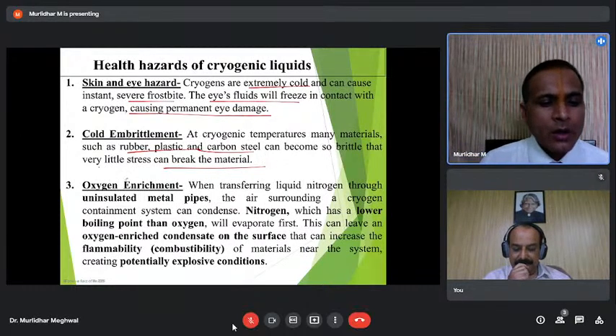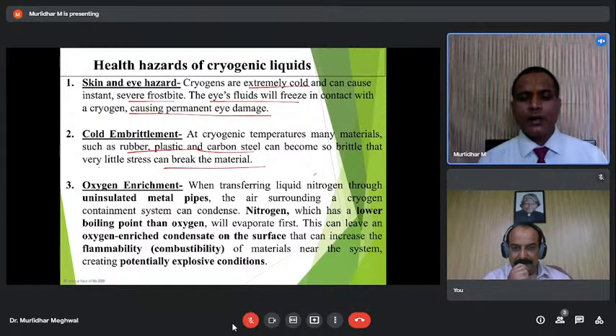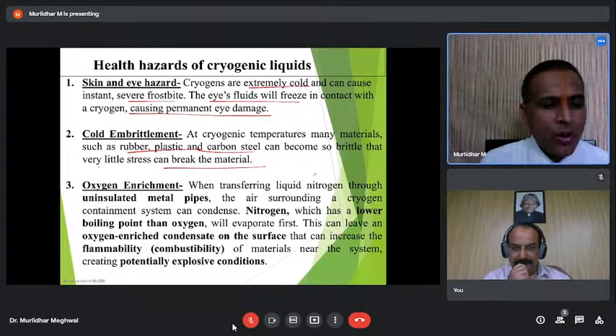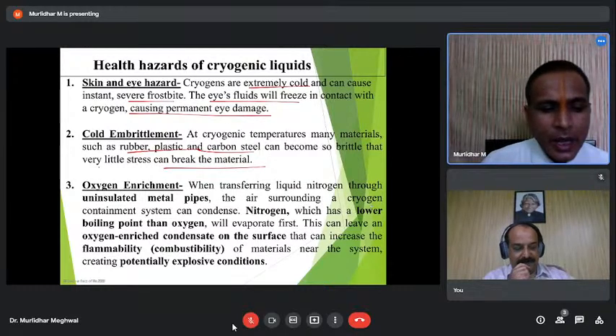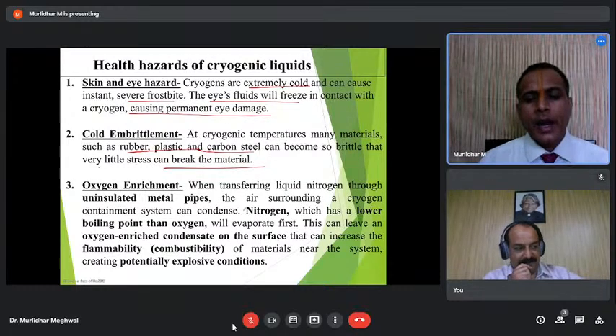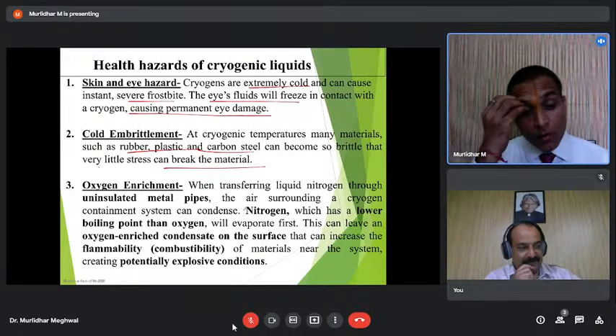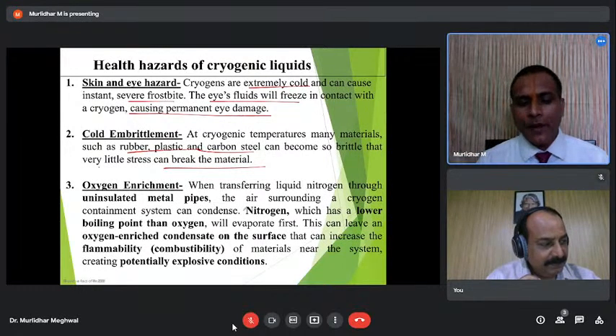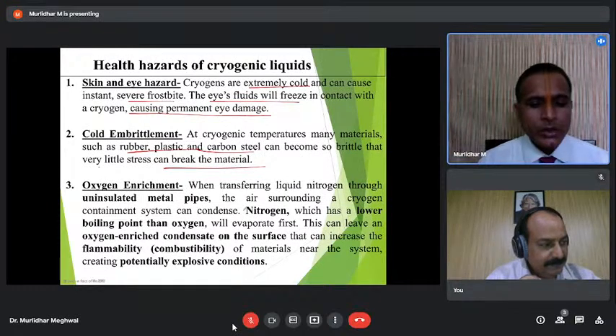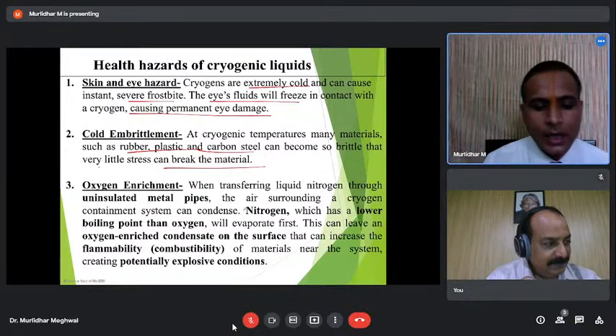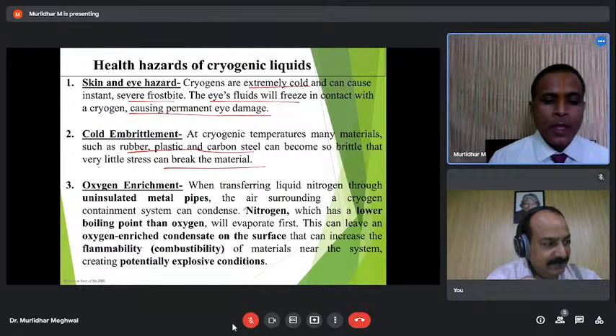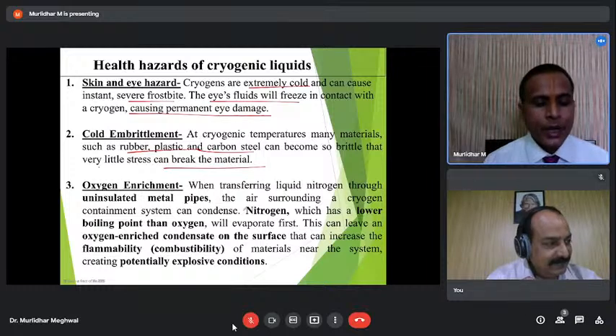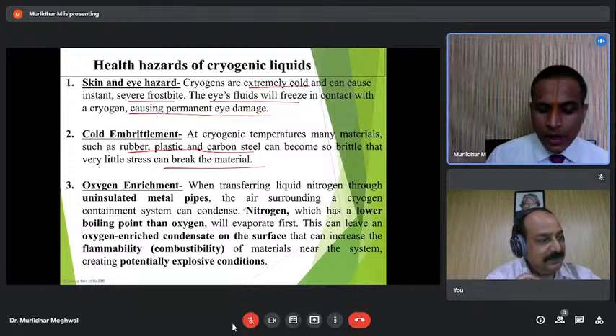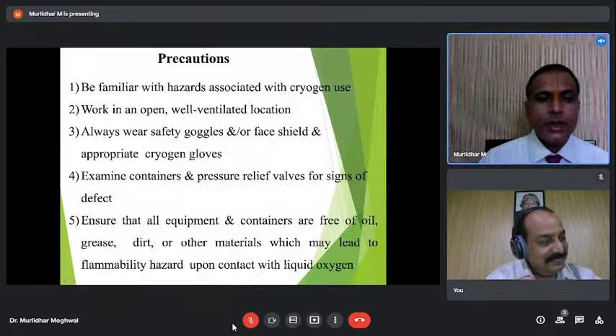Then oxygen enrichment. When transferring liquid nitrogen through uninsulated metal pipes, the air surrounding a cryogenic system can condense. Nitrogen, which has a lower boiling point than oxygen, will evaporate first. This can leave an oxygen enriched condensate on the surface that can increase the combustibility or flammability of the materials near the system, and that can lead to a potentially explosive condition. So this should be avoided, and precautions should be taken.